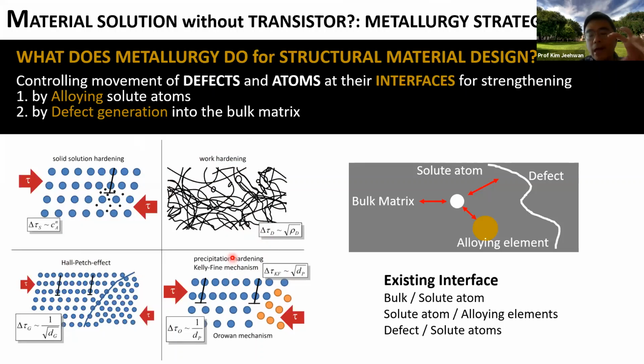They're all to make some interaction between the bulk matrix atoms and some precipitation and some solid solution, solute atoms, and some defect inside the material. That way, you can reduce the movement of dislocation so that you can harden the materials. So this is all about the interaction between the solute atoms and bulk matrix, interaction between the solute atoms and alloying element, and interaction between the atoms and the defect, okay? So we borrow this concept to have extra control on synaptic weight in the AI hardware, okay? We have been using the very traditional method in material science.